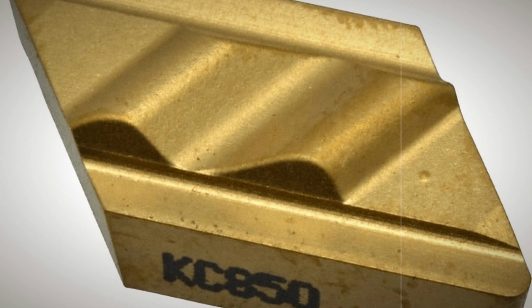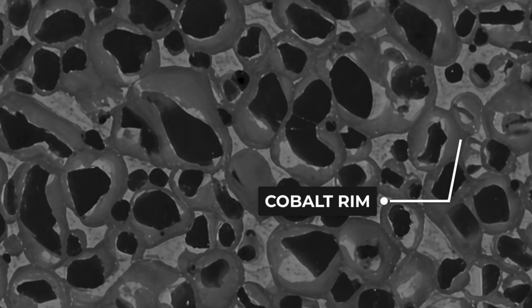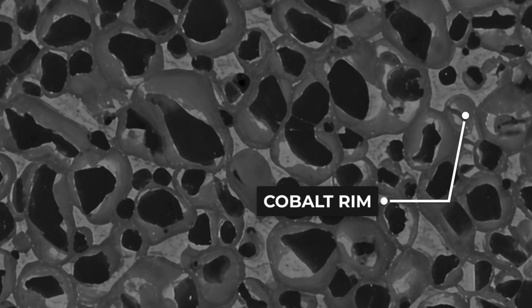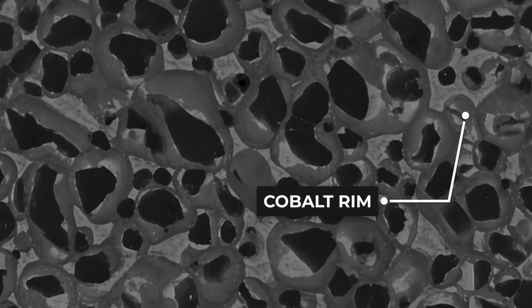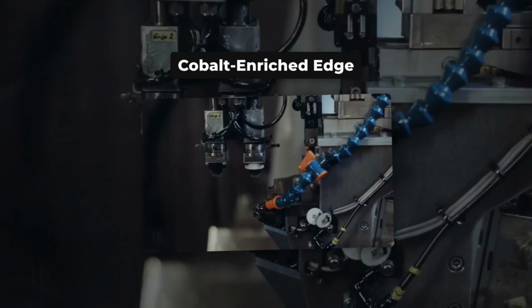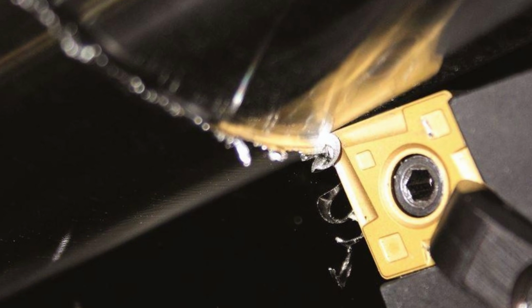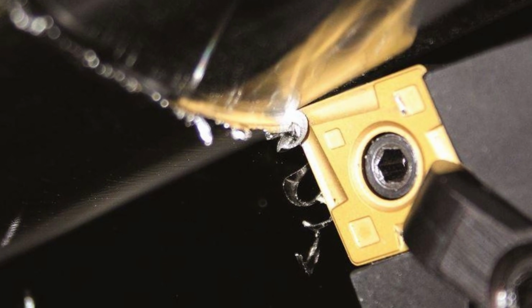And for CVD inserts, Kennametal patented cobalt enrichment, a rim a few dozen microns deep where the binder runs up to triple the bulk level, a tough skin under the hard coat that stops coating cracks from running into the edge. Turning geometry took a late leap of its own.